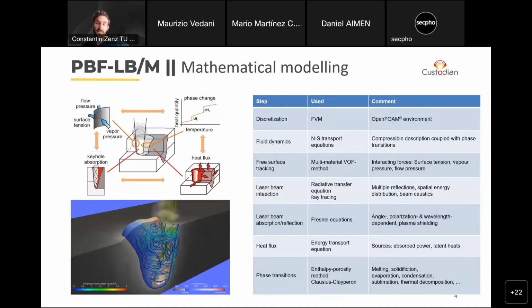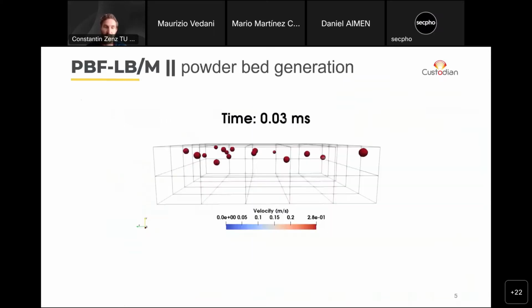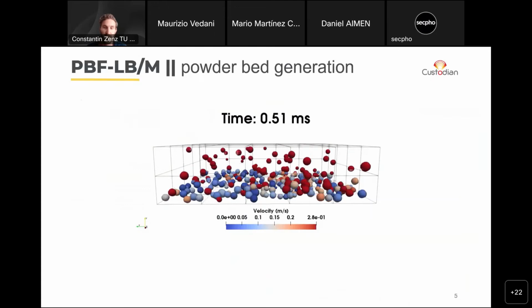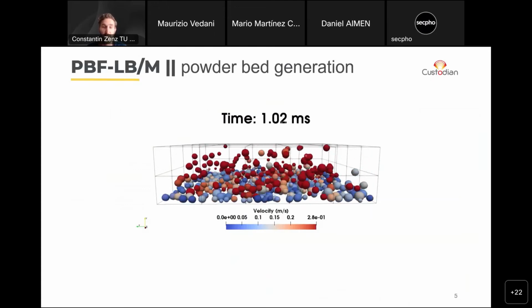And then the laser beam, which is interacting with the material. We have, of course, some angle dependent and wavelength dependent absorption and reflection modeled through the Fresnel equations. And this amount of energy which is absorbed by the metal is then conducted and convected through the material. So we have to model this energy transport. And of course, the material can undergo phase transitions, so it can melt and solidify or even evaporate and condense and so on. And then, because we're talking about powder bed fusion, there's, of course, the specialty that there is some powder involved. So we also have to, in some way, account for the powder layer.